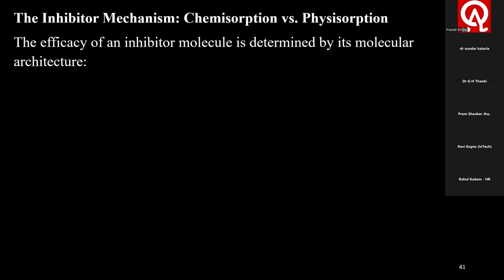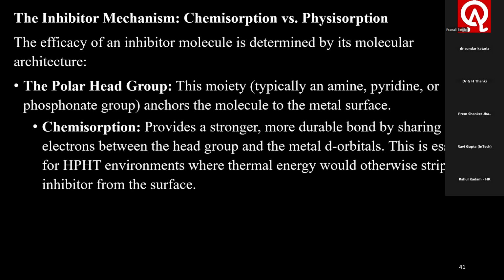The inhibitor mechanism, let us touch upon this one. Chemisorption versus physisorption. The efficacy of an inhibitor molecule is determined by its molecular architecture. The polar head group, this moiety is typically an amine, pyridine, or a phosphonate group, anchors the molecule to the metal surface. The chemisorption provides a stronger, more durable bond by sharing electrons between the head group and the metal d-orbitals, which is essential for HPHT environments where thermal energy would otherwise strip the inhibitor from the surface.